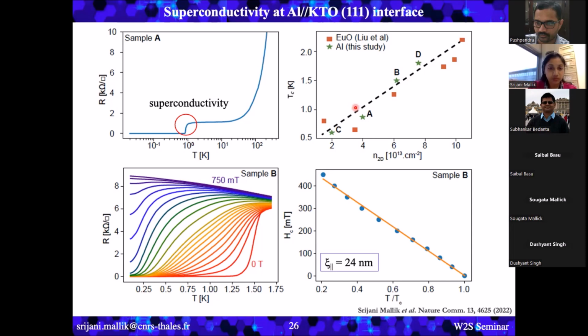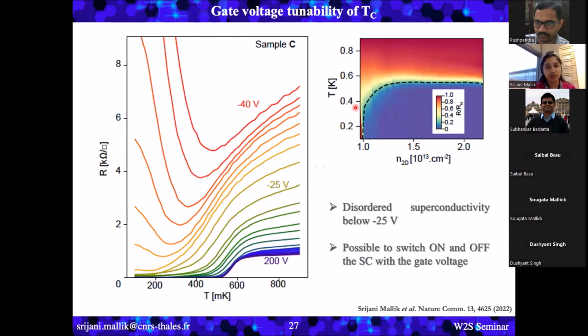Further, we tried to achieve gate voltage tunability of the superconducting Tc, and we found that below minus 25 volts, where really few carriers are present in the sample, it shows disordered superconductivity. It's because there are clusters where the superconductivity is present, but the carrier density is so low that the clusters are basically not talking to each other. So finally, we don't achieve the final superconducting state. But as we increase the gate voltage, so we are doping with more and more carriers, these clusters start talking to each other and become more homogeneous, and we could achieve the final superconducting state. So with the gate voltage tunability, we could show that it's possible to switch the superconductivity on and off.